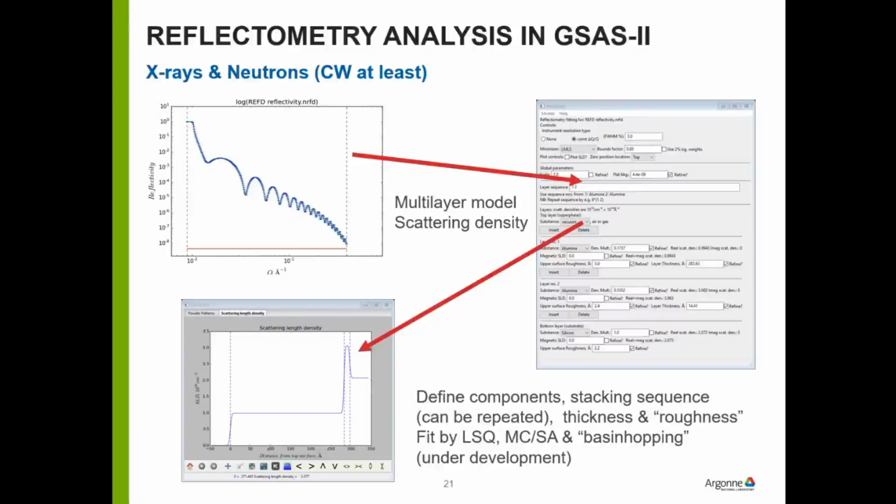Then after that, you'll get these ripples, which will depend on whatever's in the surface. You don't see anything if the surface is simply the same as the bulk. But if you put a layer of stuff on it, or multiple layers of stuff on it, then you'll get interference between what's in the layers and what's in the bulk. And that gives you ripples in the reflectivity.